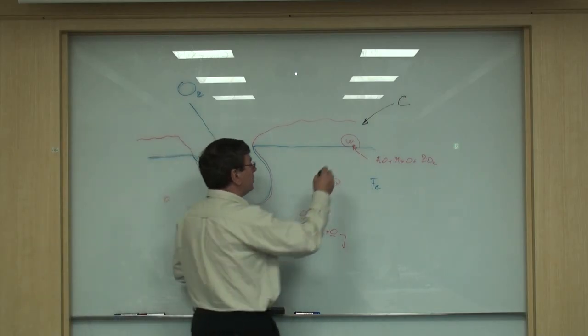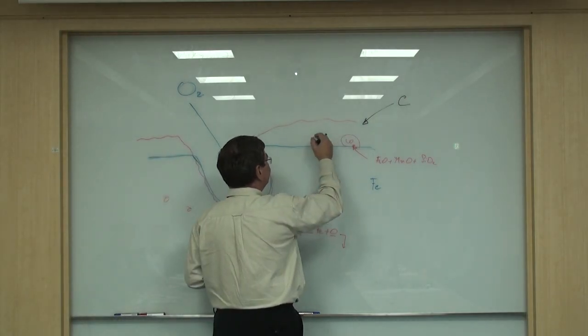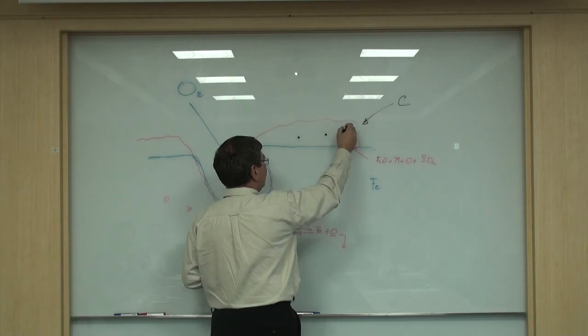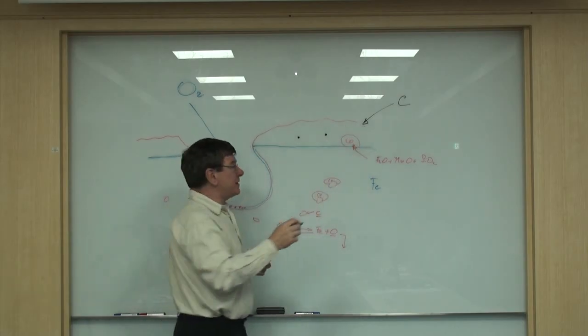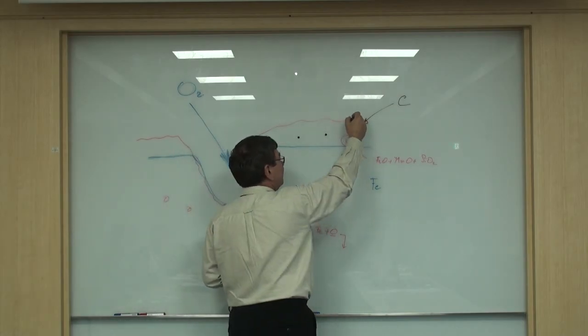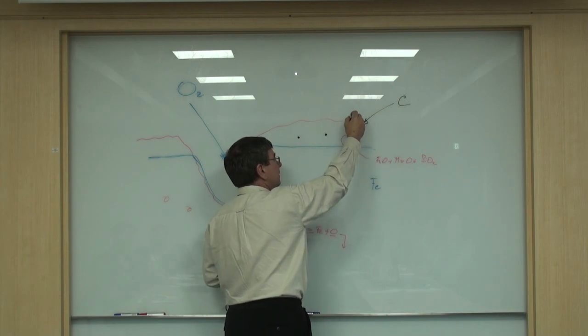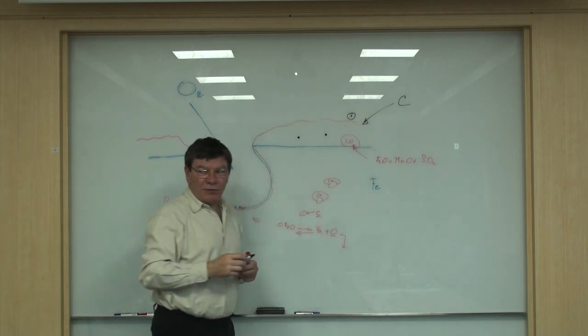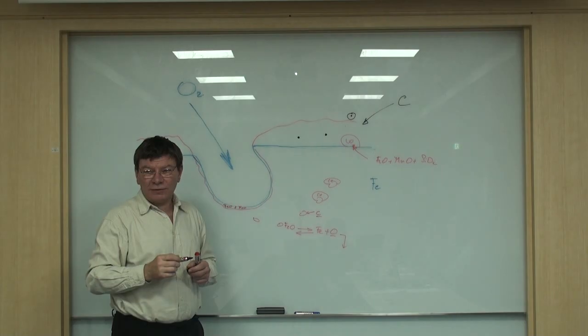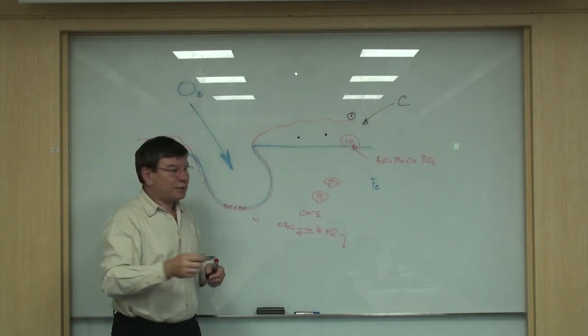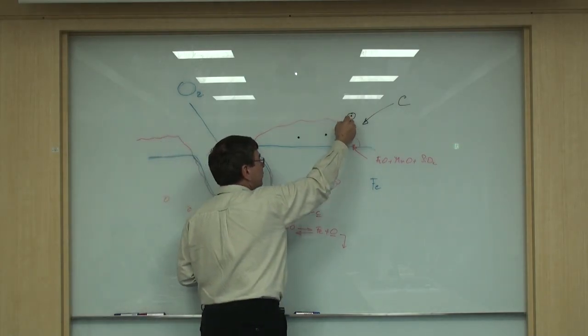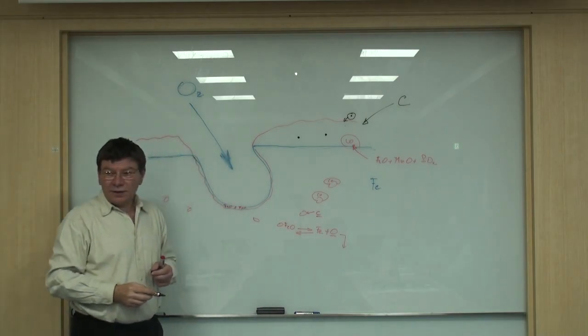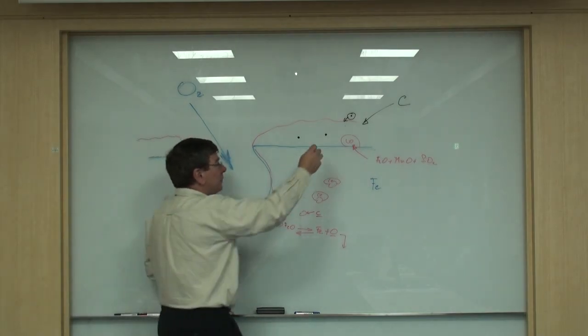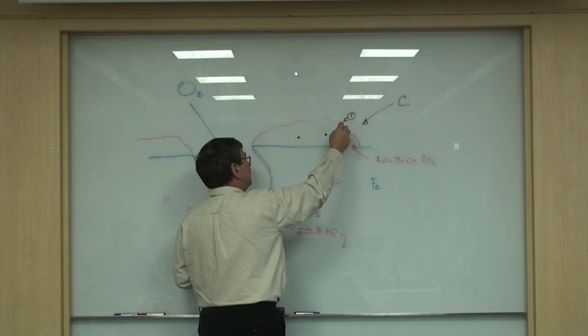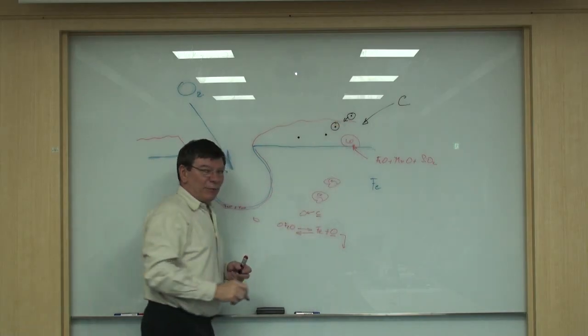Okay, we inject carbon, so we have carbon particles. Yeah. If you have high volatiles, then you send already a carbon particle with a bubble around of methane or oil, etc. So this has no way to penetrate the slag. Even if you have even a high impact, you have a carbon particle surrounded by a bubble.